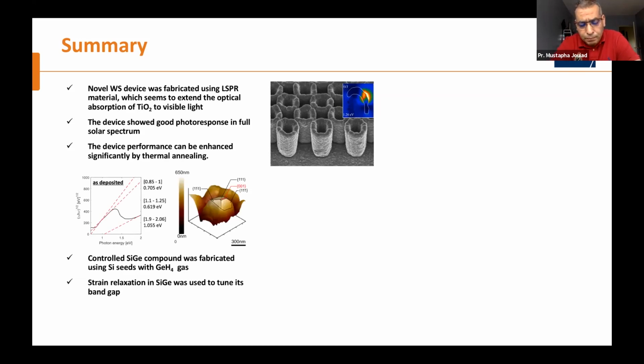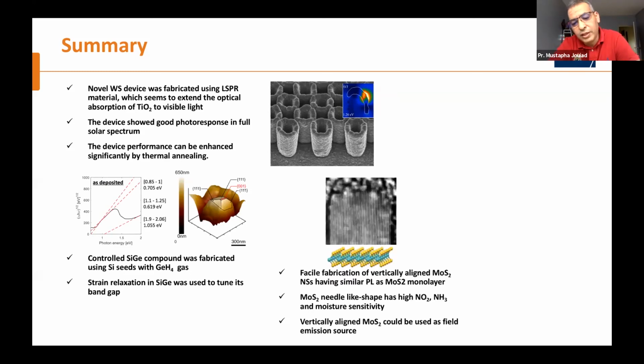The second example, I showed you how we can engineer the band gap in silicon germanium. We did straightforward fabrication of silicon germanium, but with a specific annealing, we were able to engineer the band gap. Then I showed you how we did facile fabrication of vertically aligned MoS2, which have a very specific orientation of their needles. They are needle-like in shape, and they have very good properties as for monolayer. They are also highly sensitive to some gases and moisture.